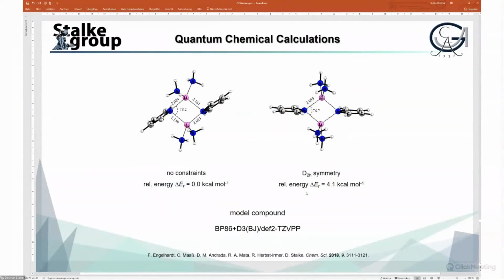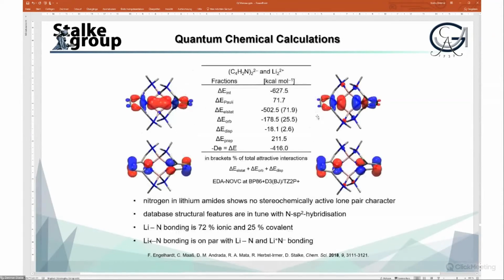So if we look to theory, of course, theory needs to be looked at to come up with some energies. Then this step arrangement of the pyrrole rings in this molecule, where we have the alignment parallel to the lines, is 4.1 kilocalories more stable than the bisection mode. And it's a good hint. 4 kilocalories means a lot in this sort of chemistry.